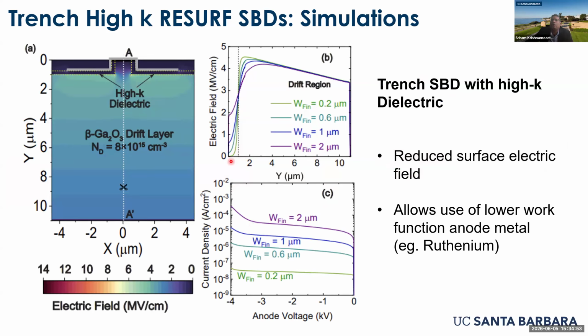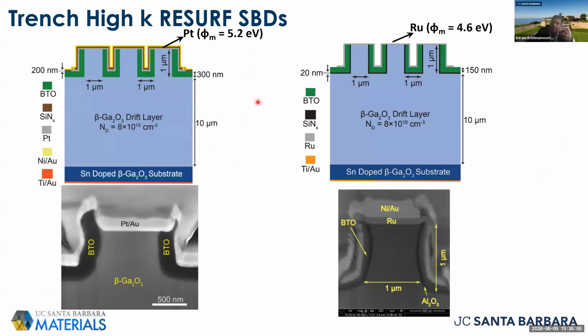So we further simulated these devices, and if you engineer them carefully with the right aspect ratio, you can get to very low surface electric fields in these devices. Okay, and you can push the peak electric field within the semiconductor, and so this was experimentally realized using platinum and ruthenium as the metal layer, and barium titanate as the high K oxide.